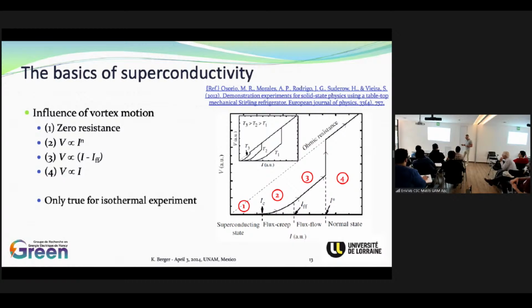If you look at the voltage current relationship of a superconductor, in fact, there are different parts in this relationship. In the first region, below what we call a critical current, but it's not very critical, there is a full superconducting state where the resistance is zero or very close to zero. We cannot measure this kind of resistance. In the second part of the relationship, we have a flux flow, which means that the vortices are moving and generating some electrical field and losses. So it is still a superconductor, but with losses. It's not a perfect conductor.